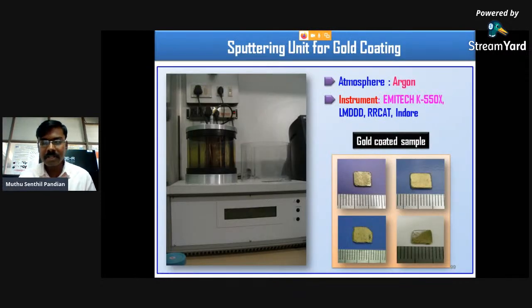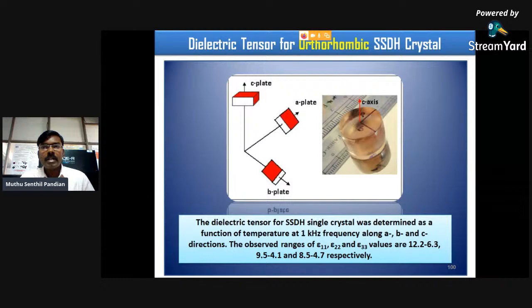Then we have compared the electrical properties of the conventional and SR method grown crystals. Some crystals we have selected and carried out the electrical measurements for comparative purpose. The dielectric permittivity of a crystalline material is a second rank tensor. For an orthorhombic crystal, there are 3 independent components. For a monoclinic crystal, there are 4 independent components. So normally we have selected a particular direction. In the conventional method, what is the dominant plane? So this is the A direction for the conventional method. Similarly, we have to choose the B direction. Similarly, we have to choose the A direction for the SR method also. And at identical thickness, what is the dielectric permittivity value?